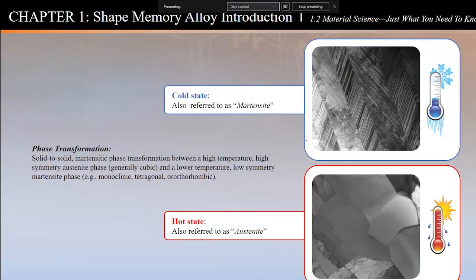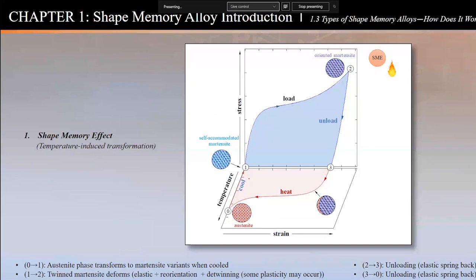Here is one version of the shape memory alloy, and I'm going to describe it here. So we start, hopefully you can see my little pen here. I'm at 0. I'm in slide 13. So we start from 0, and this is the austenite phase, and I just told you it's the parent phase and it's the cubic phase. I cool it under 0 stress, 0 load to 1. Nothing happens. It just accommodates this little square that you see into some twin mode that you see here. Nothing happens. No macroscopic changes because that twinning that's occurring is very small.